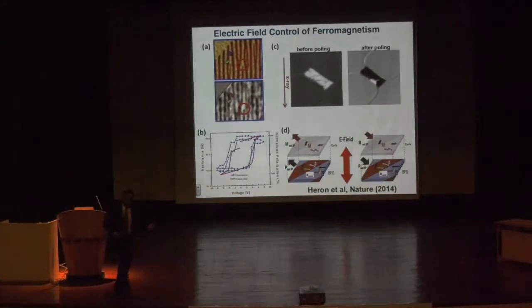Okay. So what it's telling you is that if I apply of the order of 6–8 volts, I could switch my ferroelectric, and I could also switch my ferromagnet by switching the spin valve. You could go back and image that by using photoemission microscopy. This is a small island of the ferromagnet. These are the metal pads, and you can do it before poling, and after a single pulse, it goes from white to black, meaning that the magnetization has switched by 180 degrees.